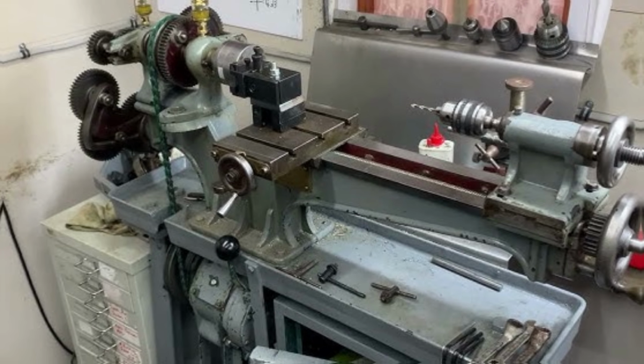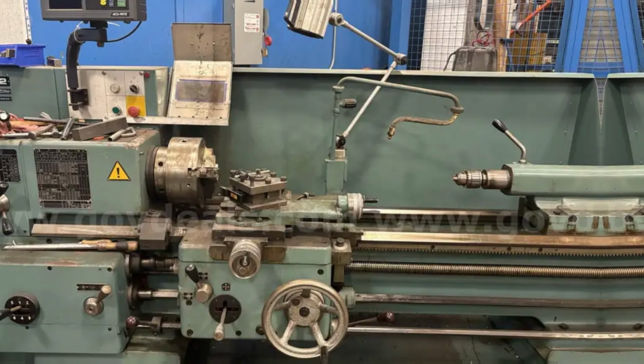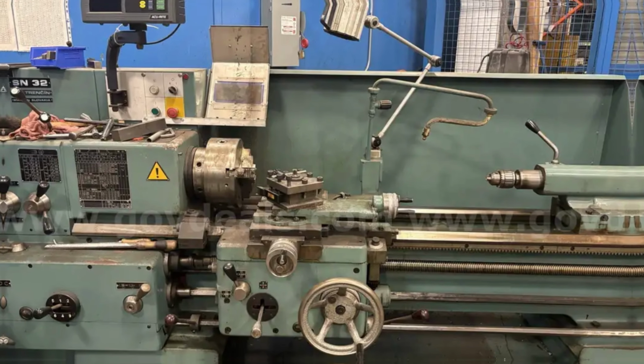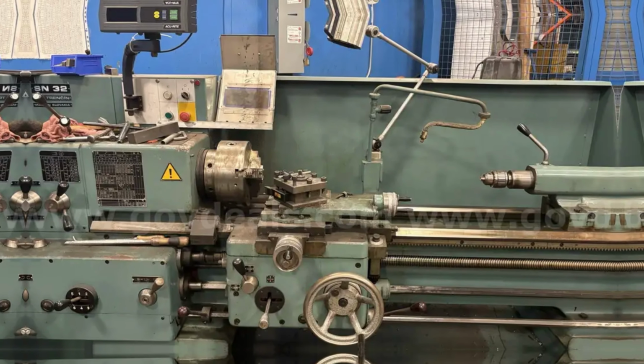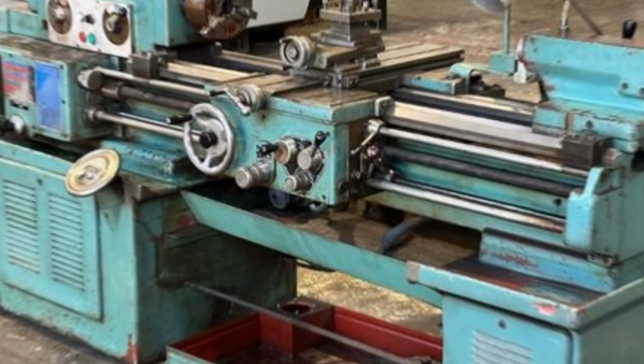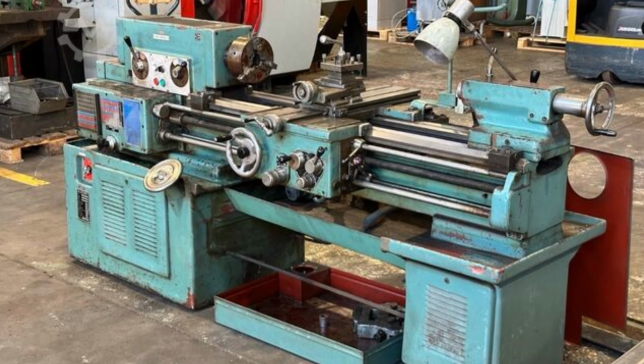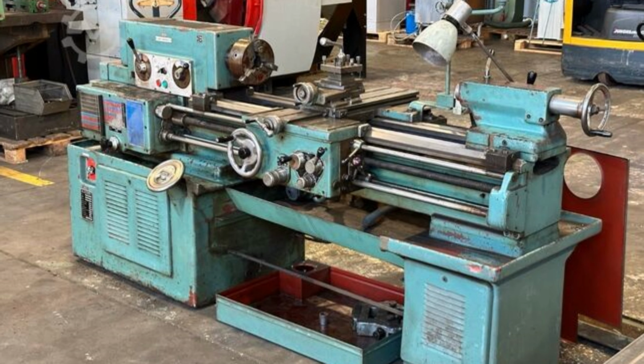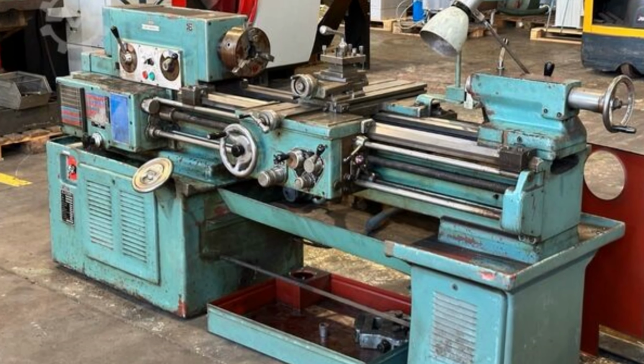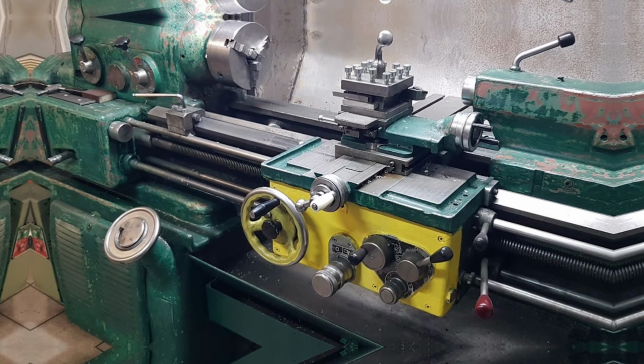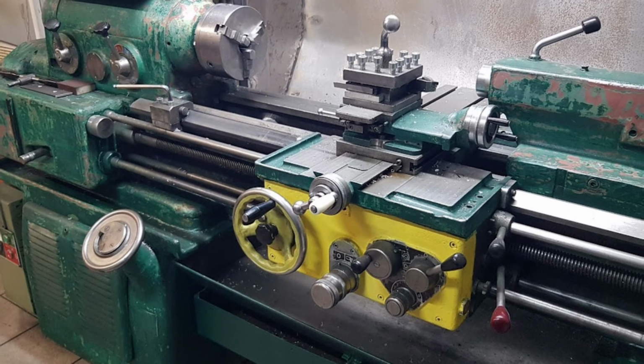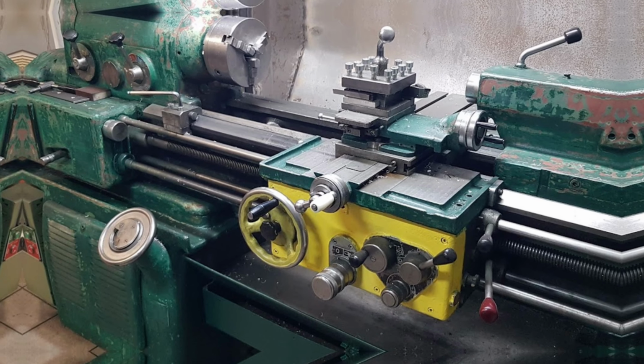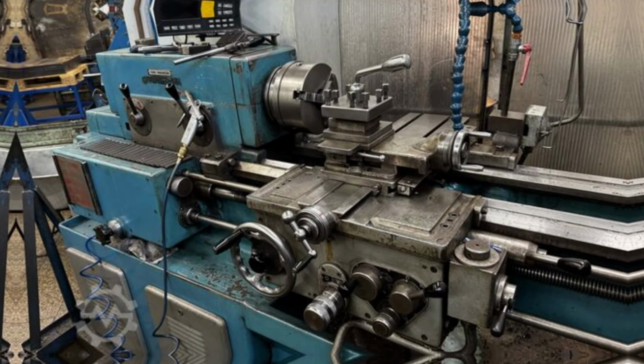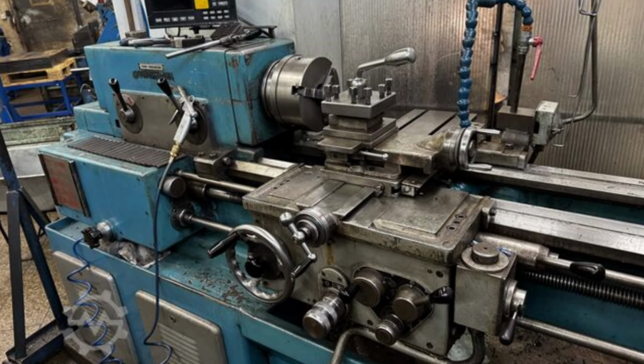But that hardness disappeared the moment friction heat from cutting operations raised the tool's temperature above 400 degrees. Machining hardened steel components generated temperatures exceeding 800 degrees at the cutting edge. The tool softened, deformed, and failed with mechanical inevitability. British metallurgist Robert Mushet had solved this problem in 1868 with his revolutionary tungsten steel alloy. Self-hardening steel, he called it, though the real innovation was heat resistance. Mushet's steel retained hardness at temperatures approaching 600 degrees, allowing cutting speeds that carbon steel could never match.